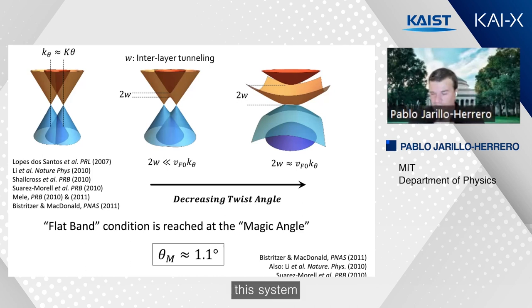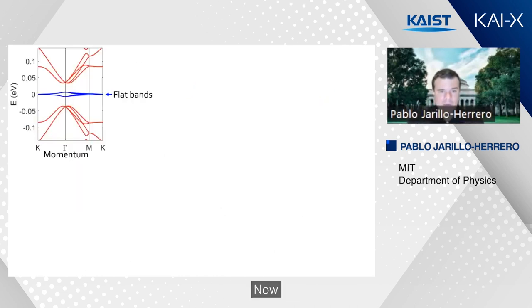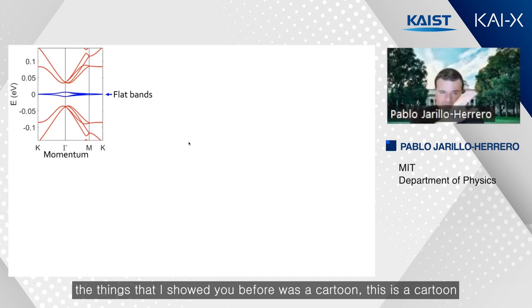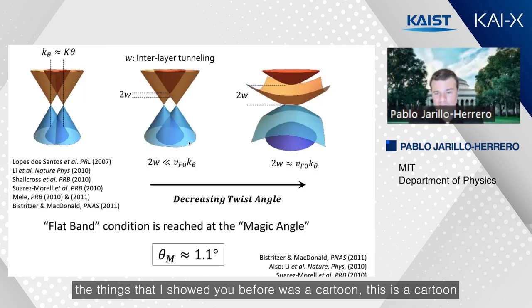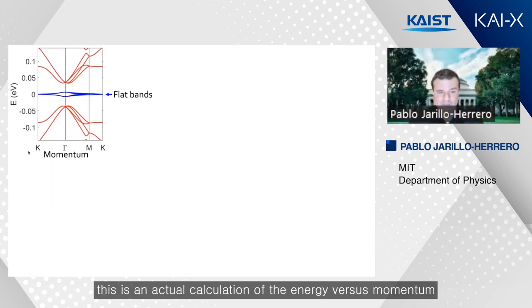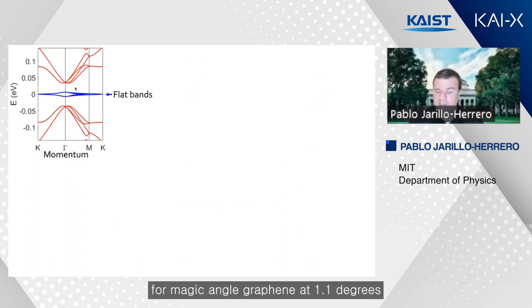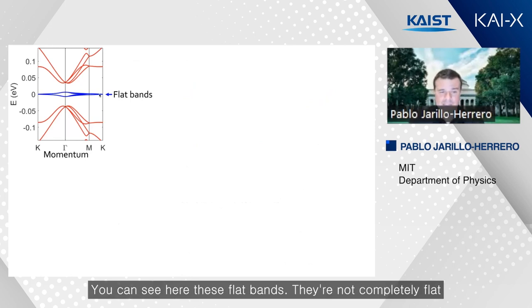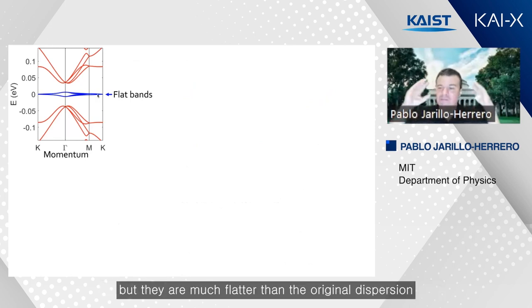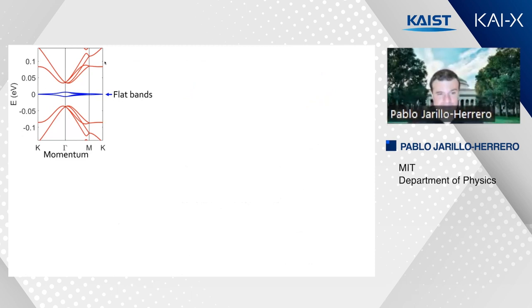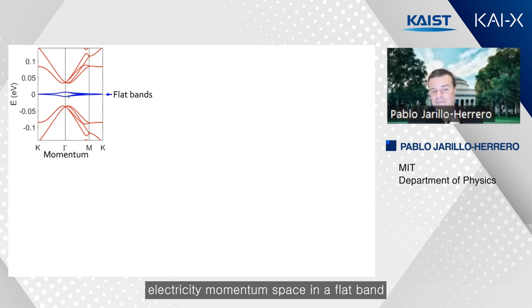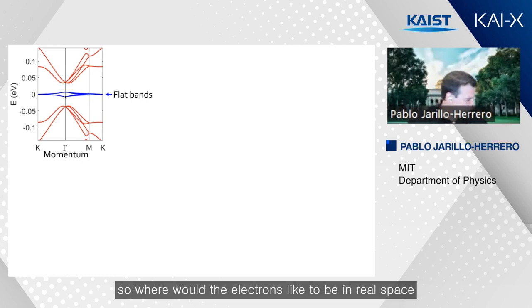about this system. Now, the things that I showed you before were a cartoon. Okay, this is a cartoon. This is an actual calculation of the electronic structure, energy versus momentum, for magic angle graphene at 1.1 degrees. You can see here these flat bands. They're not completely flat, but they're much flatter than the original graphene dispersion. And if you think about electrons in momentum space in a flat band, where would the electrons like to be in real space?